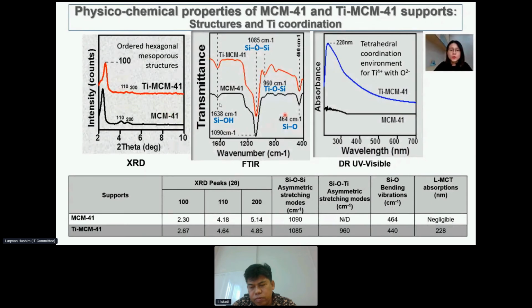So now we look at this FTIR result. Based on this FTIR result, we can indicate that there is a presence of this linkage, which is titanium-oxygen linkage, that's present in this modified support, while the pure MCM41 shows the presence of the linkage between the hydroxyl group with the silicates, as well as the linkage between the silica oxygens and silicas.